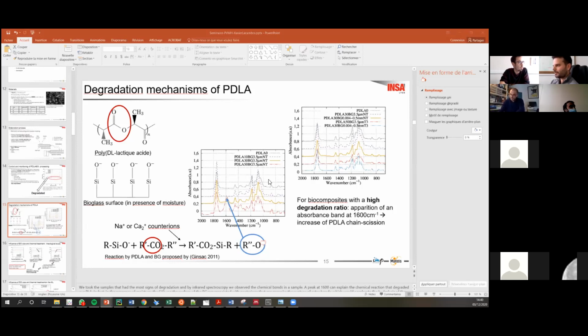Okay, yeah, we think... are you stopped? No. We think that the mechanism behind this degradation is the presence of some reaction on the surface of the bioglass, as I explained. If we increase the content of bioglass in this kind of composite, there's more interaction between the PLA and the bioglass, so it increases the hydrolysis of this PLA.